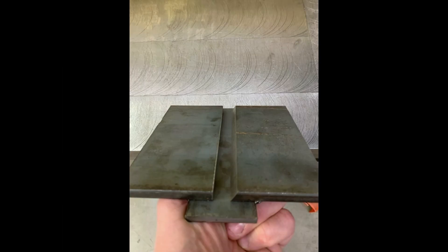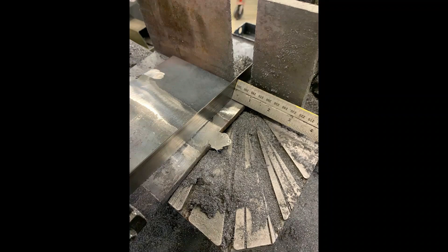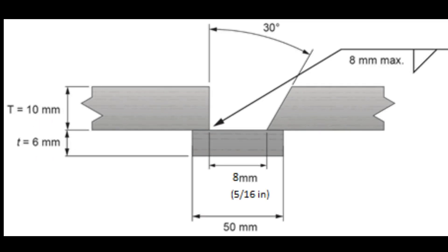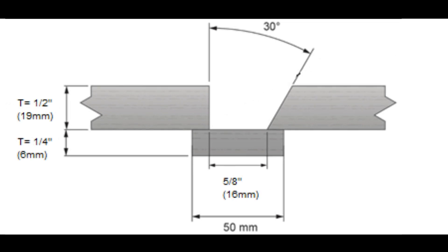The test center is responsible for providing the plate. However, in the event that you are responsible for putting your plate together, it's important that your tack welds be no larger than three-quarters of an inch from each end, as the tacked ends get discarded when processing for destructive testing. If the test plate is going to be x-rayed, we don't want any tacks in the weld zone — tacks could show up as lack of fusion under x-ray. Your 1GF, 3GF, and 4GF tests have a half-inch (13 mm) root opening, and your 2GF test has a 5/16-inch (8 mm) root opening. When changing to larger diameter wire with flux core and metal core, the root opening also changes to five-eighths of an inch.